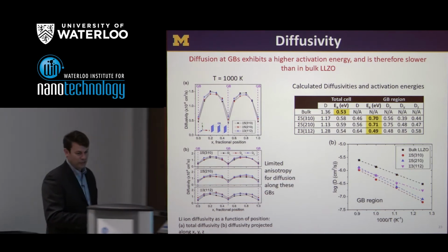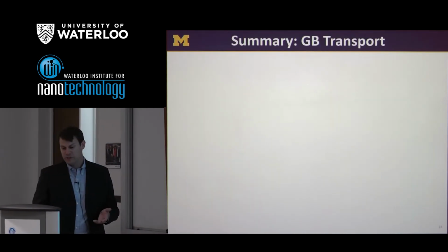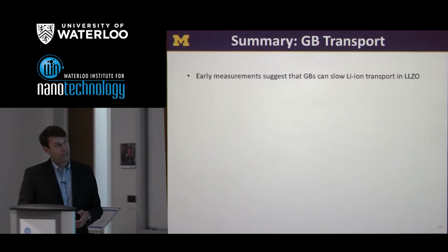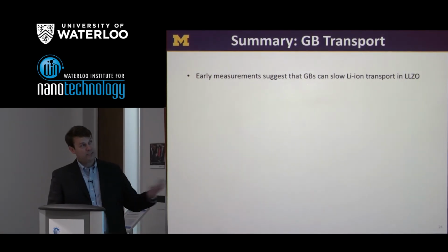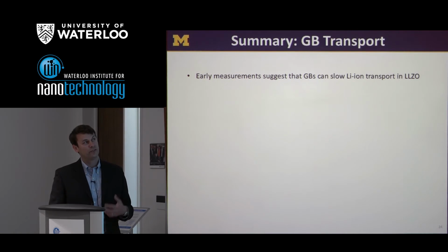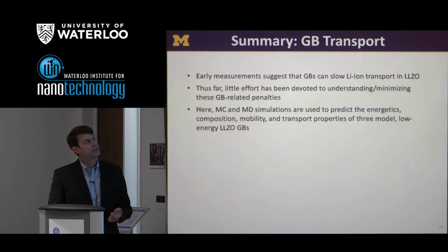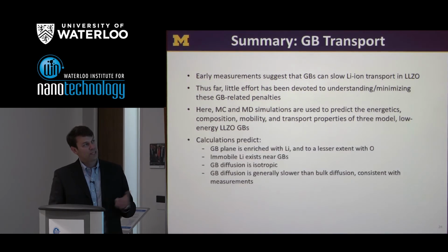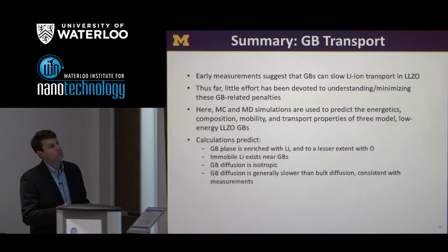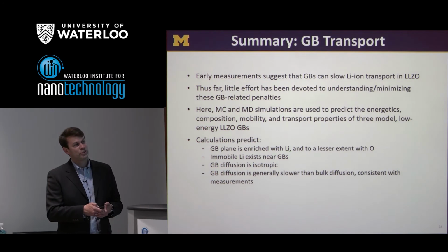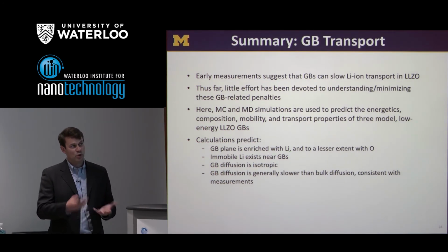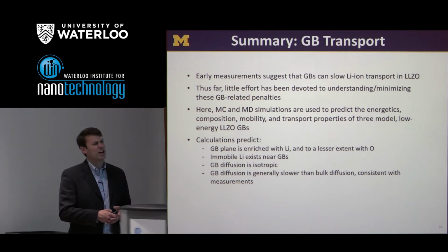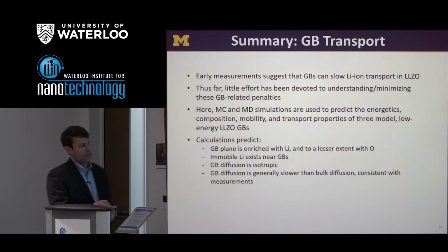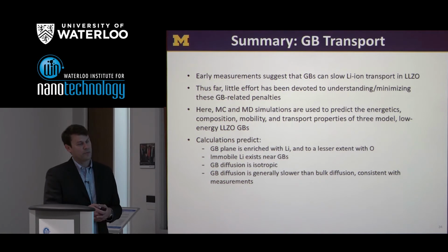So basically what we're seeing here in this case, again, at least for these model grain boundaries, is something consistent with the experimental data, that is slower transport along the grain boundaries as predicted by these calculations. We also can get information about the composition. Some enrichment of lithium and oxygen was observed. What lithium is immobile is largely focused on the grain boundary planes. And that grain boundary diffusion appears to be isotropic.